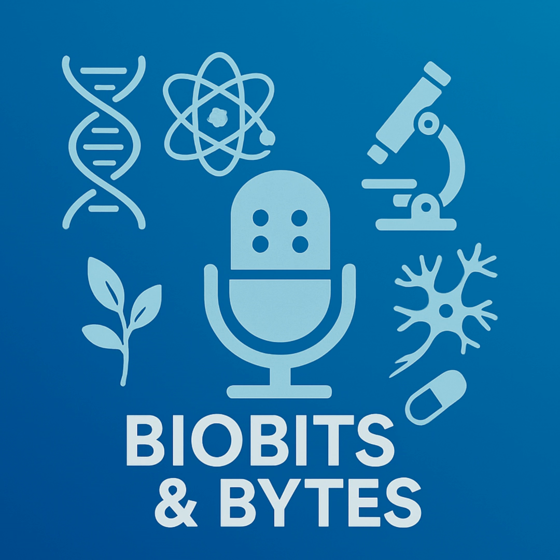Right, aggregation again. Exactly. Plus, a bare surface can interact randomly with cells and proteins, which might trigger an immune response or just get the particle cleared out of the body too quickly. So the coating is like a shield or a stealth cloak. Kind of both. It does several key things. First, it dramatically improves stability and dispersibility, keeps them from clumping. Second, it can reduce those nonspecific interactions, maybe helping them circulate longer or avoid being instantly eaten by immune cells. And third, and this is really important, the coating provides a surface that scientists can then chemically modify.